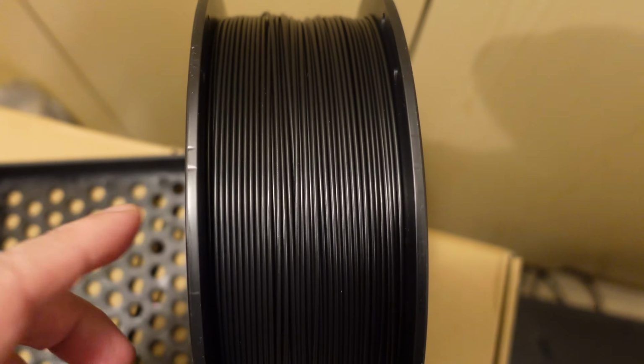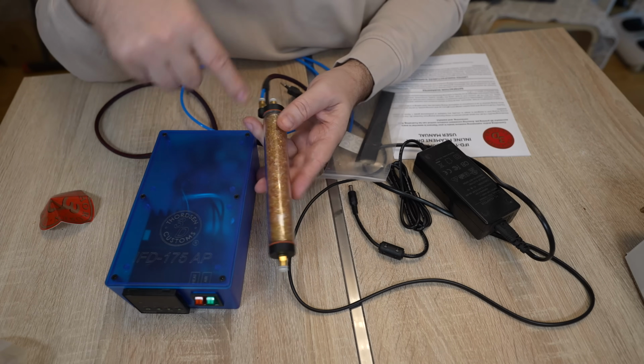And maybe they should use some better spools, maybe some cardboard spools which can be dried even on 120 degrees Celsius in the oven, because this closed plastic spool, which cannot survive even temperatures above 90 degrees Celsius, are just not good enough. I mean, drying on 85 degrees Celsius inside this closed spool, maybe it is possible, but let's say in 5 days or something like that. So I can see a lot of possibilities in this filament, but it must be properly dried. Actually, I have an inline dryer on the test. Maybe I'll try to use it with this filament. We will see, because it is independent from the spool. But more about that in some future video.